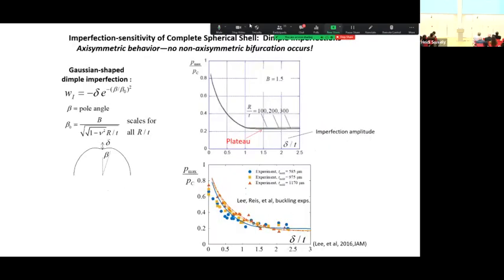Here's the same results, but here plotted as the buckling pressure, and this is the maximum pressure that this shell, in the presence of the imperfection, can carry. This is the imperfection amplitude divided by the shell thickness. And I didn't mention, and it's not obvious why this is, but these results normalized this way are independent of the shell thickness. And so lo and behold, you see that what emerges here is this plateau at just about 20% of the classical pressure. And even for quite big imperfections, it doesn't get below that.